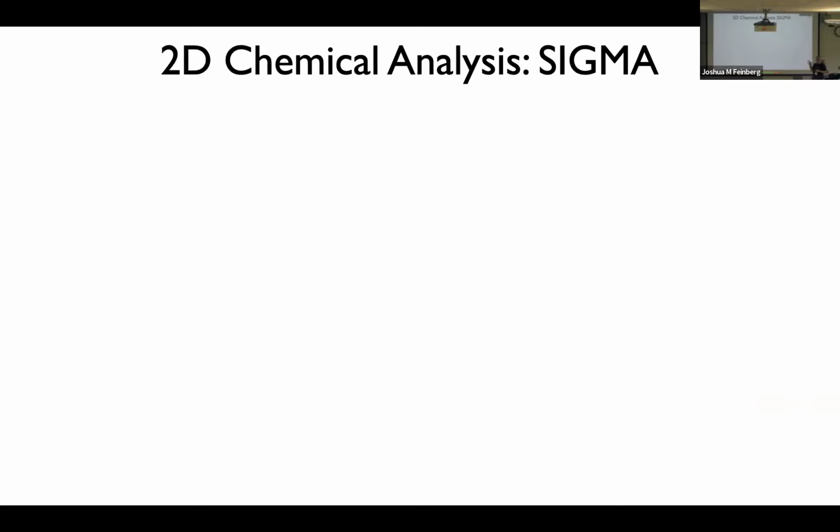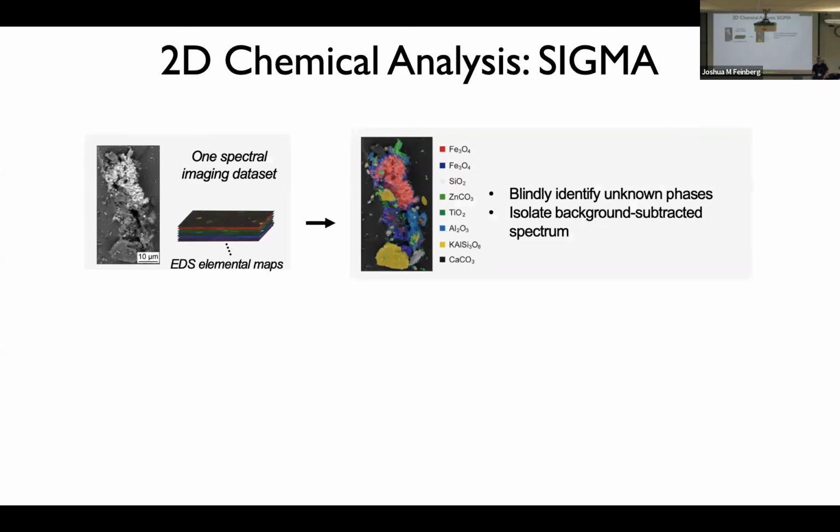So next, I want to talk about the chemical mapping side of this. There's a limit to what you can do with backscattered electron imaging, right? That just gives you intensity brightness, okay? It's not very discriminatory. What you really want to do is chemical mapping. And very often what we find, looking at the presentation so far, in any number of examples, is that you're dealing with chemical mapping of samples which are very fine-grained. So the features in your sample are smaller than the interaction volume of your EDS. And so you're struggling with, okay, how do we treat chemical mapping data of very fine-grained things